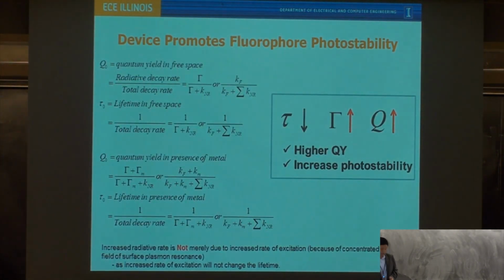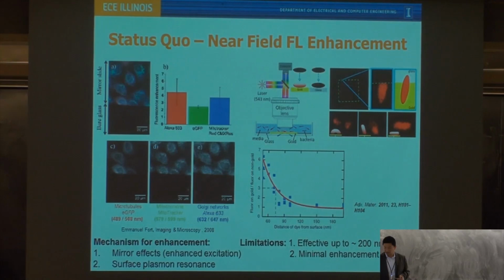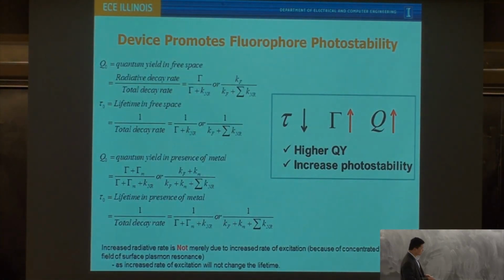We also did some back-of-envelope calculation to find out how we use this lifetime to predict the photostability of the fluorophores. Our general consensus now is that with the decrease of lifetime, we have a higher decay rate, and we have a higher quantum efficiency. That's what we measure experimentally. The data is published in APL. But this is not the focus of my talk today.